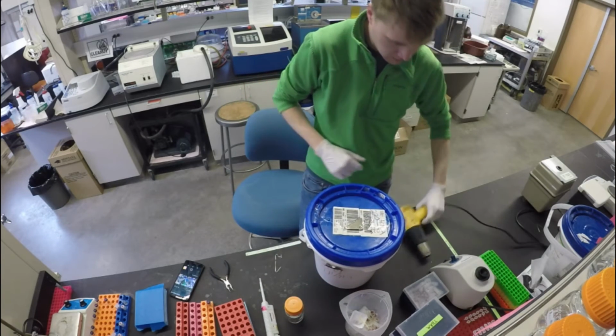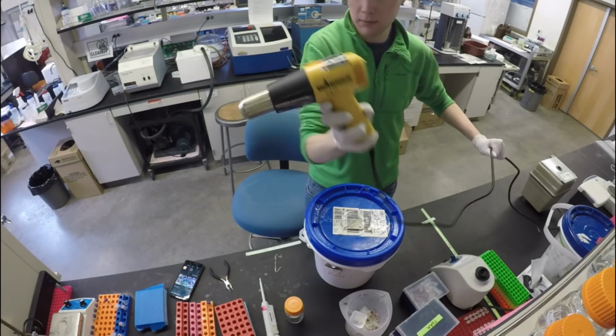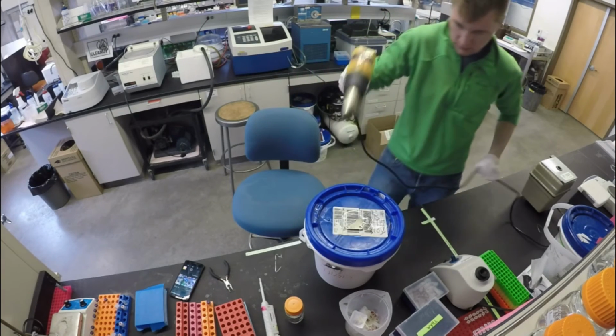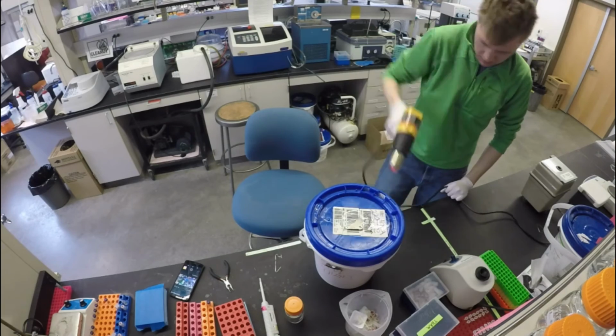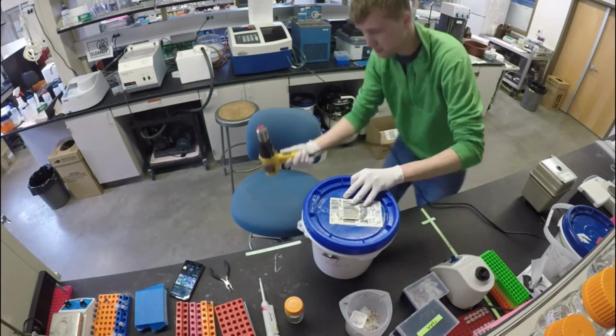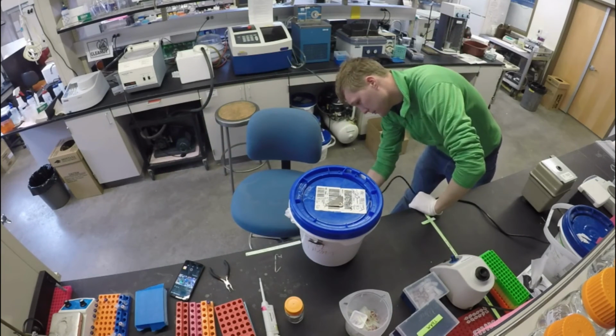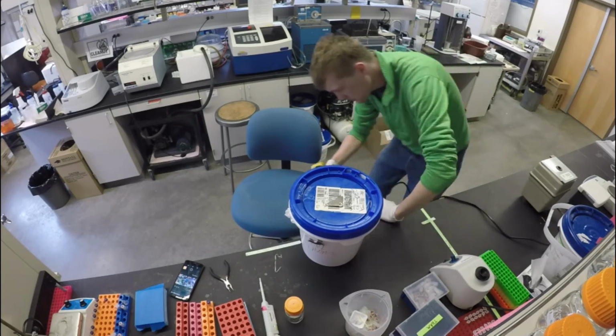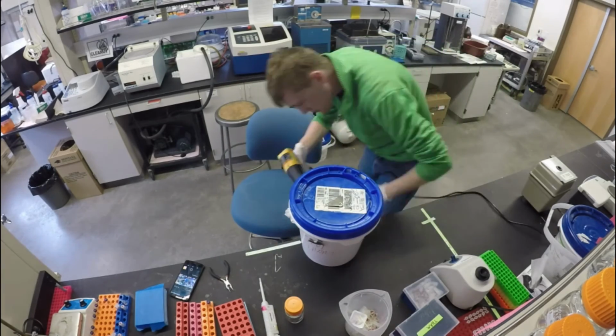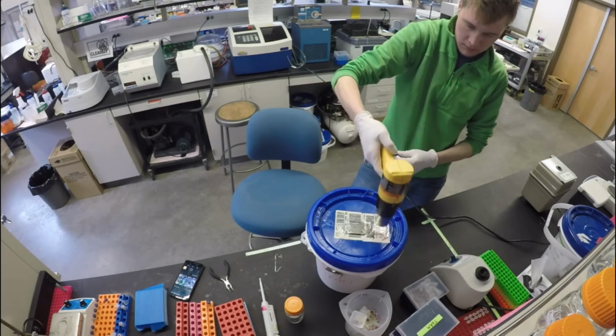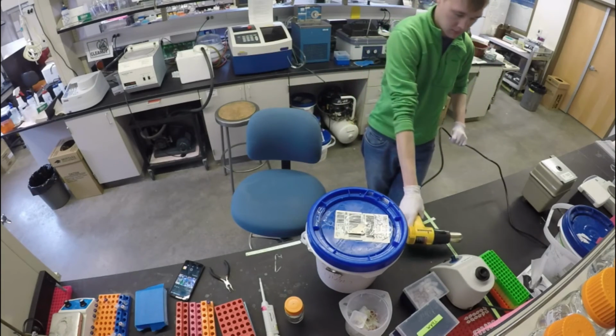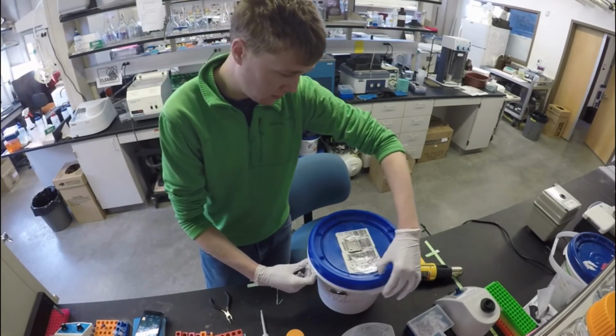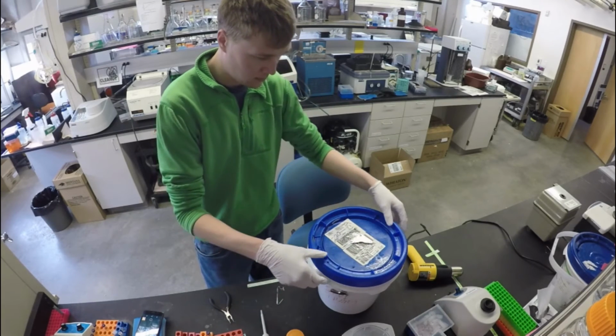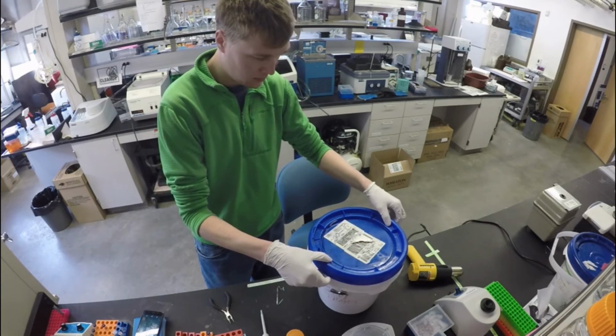Now, I'm kind of a lazy person, so I'm actually going to speed up the process of getting the fumes in the container going by adding some heat. This is just a heat gun. You do want to be careful you don't do this with a sealed container. You'll notice that this is a screw top lid, and I leave it ever so slightly cracked just so you don't build up pressure. After somewhere between 20 minutes or maybe an hour, depending on the part, you can go ahead and open it.